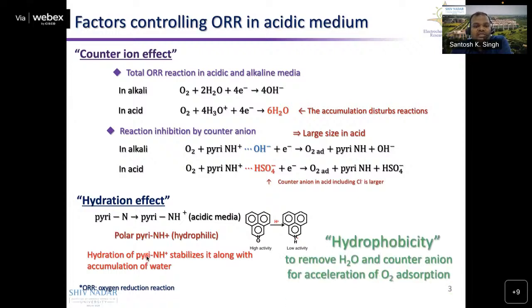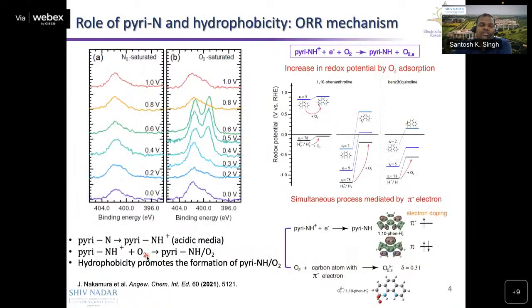So we know the problem nowadays with the pyridinic nitrogen, that it has the counter anion effect and the hydration effect. So to remove this counter anion effect and the hydration of these active sites, if we can introduce hydrophobicity to the active sites, then it can remove the water molecules and also accelerate the adsorption of oxygen during the catalytic reaction. So we used this concept to prove this point.